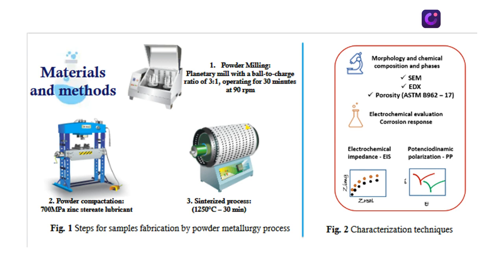The uniaxial compaction process was then carried out, adding a zinc stearate lubricant to the powder mixture and applying a load of 700 megapascals. Once the compaction was completed, a sintering process was carried out at 1250 degrees Celsius for 30 minutes. Once the samples were obtained, morphology evaluation was carried out by electron microscopy and porosity estimation, and the electrochemical and corrosion resistance evaluation by electrochemical impedance and potentiodynamic polarization, respectively.